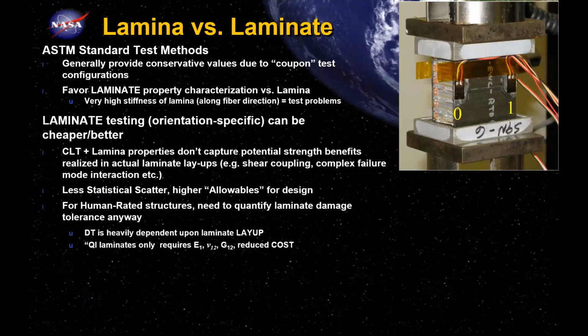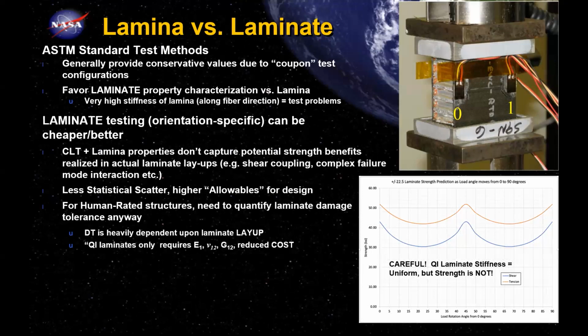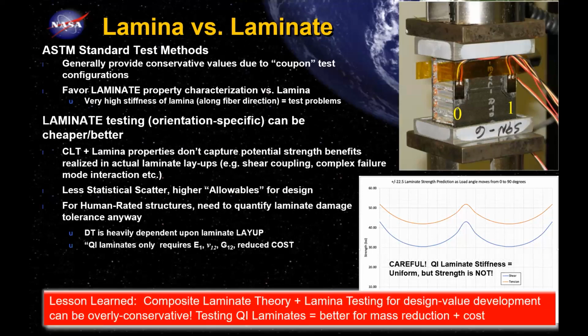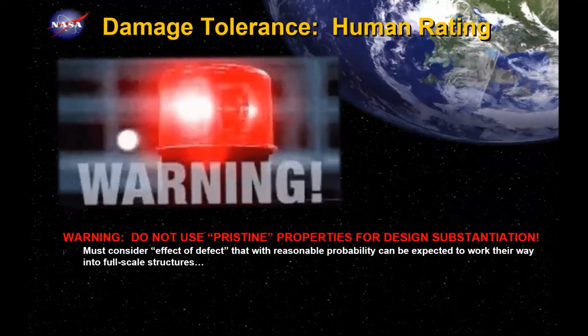This is just a word on lamina versus laminate testing. I learned this from the F-22 and F-35 programs. When you isolate and do lamina level testing, like a 0/90 lamina, for those that are familiar with ASTM standard testing for composites, and you're trying to get lamina properties, you'll find that your statistical properties end up being lower than if you test the laminate and then use reverse composite. It's a little bit complicated, but you'll actually improve your strength values. This would really be for pristine strength, or for things like modulus or stiffness. So, big thing on damage tolerance.